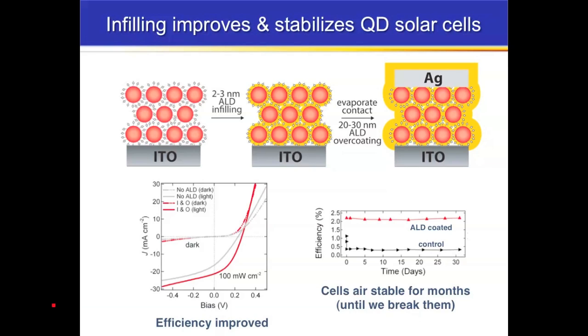And what we see in the performance is basically a doubling of the efficiency from a very low value of 1 to a slightly better value of 2%. Okay? But the main thing we were looking for is the stability. And the ALD-coated film here is totally stable out for very long times, whereas the uncoated material, you can see dies within seconds of air exposure and then kind of lives on at a very decrepit state here for a long period of time. And so by using this ALD approach, we're able to basically solve the stability problem for quantum dot materials. This allows the entire field basically to take these materials out of the glove box and do science at their own pace.